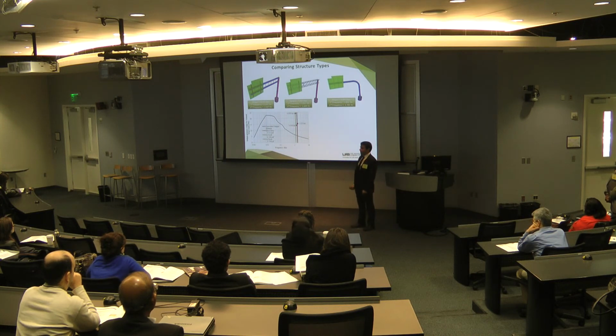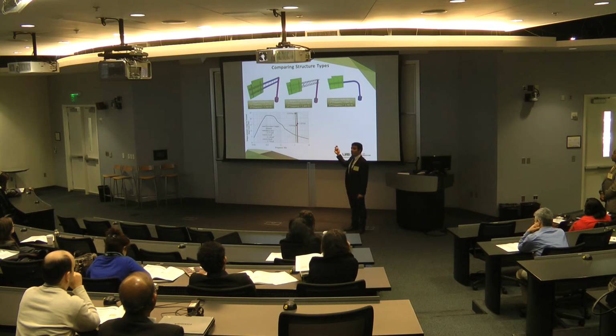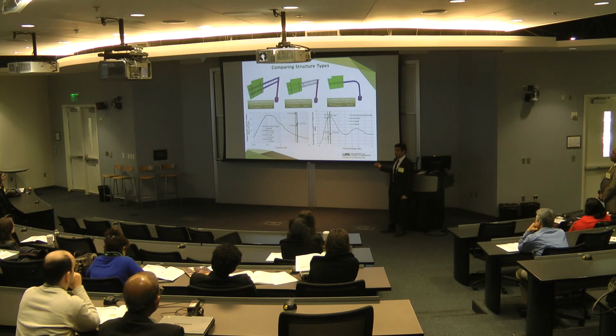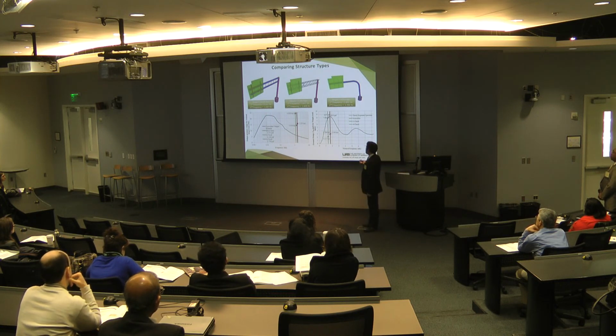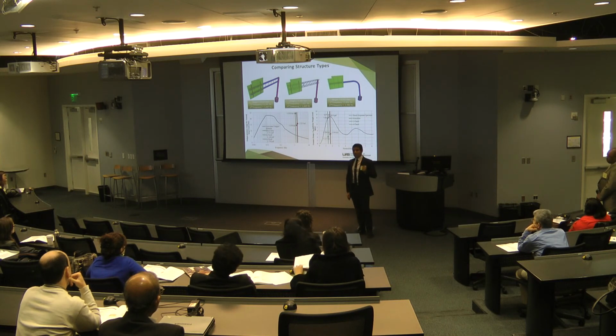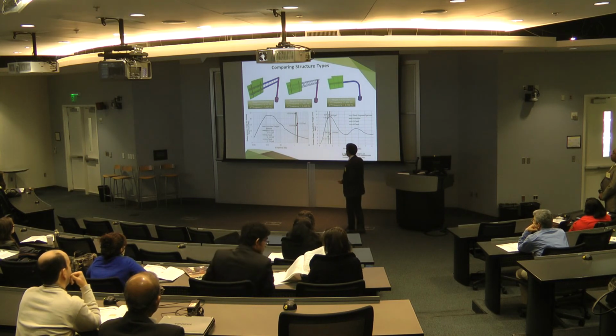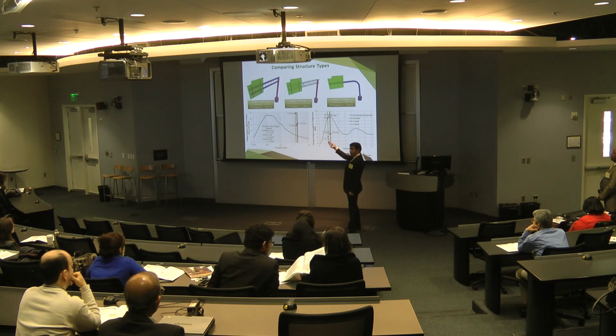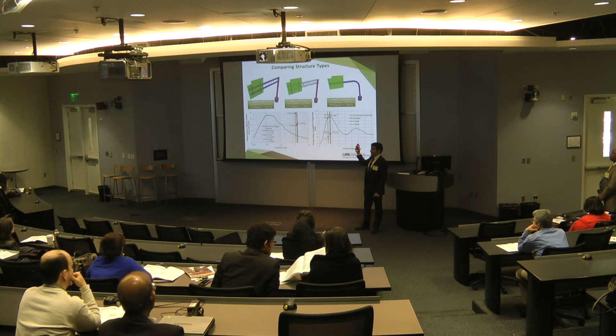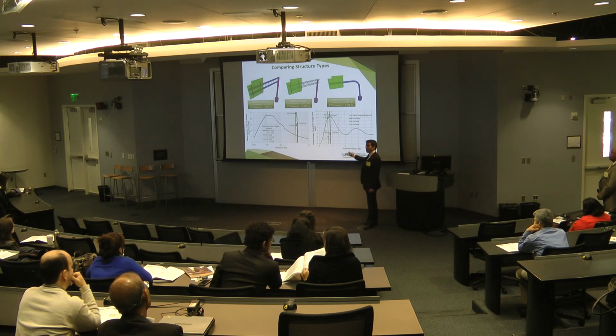As for the last one, it has the highest fatigue stresses for two reasons. It's low frequency, and the second reason is the high exposed area to wind. I have two stocky members. This graph is just for convenience. This is for truck-induced wind gust. As you see here, 1.7 hertz is the peak response. The first structure, even though it has lower frequency than the others, was shifted away from this value. That's why I got the least fatigue stresses.